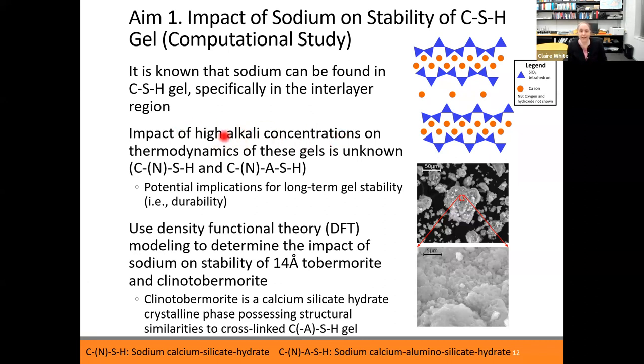So the impact of high sodium concentrations is not well known. And so what we've done here is use density functional theory, computational chemistry, to determine the impact of sodium on some model phases. As you're probably aware, with computational chemistry, there's a limitation to what size systems you can study. Larger system sizes, you tend to use force field based techniques. Here we're using density functional theory because we want to get accurate information on the energetics of the system. But we have to compromise on the system size. And so that's why we're using crystalline analogs for this disordered gel, the gel that we know is not a crystalline phase. So specifically here, we're using what's known as 14 angstrom tobermorite.